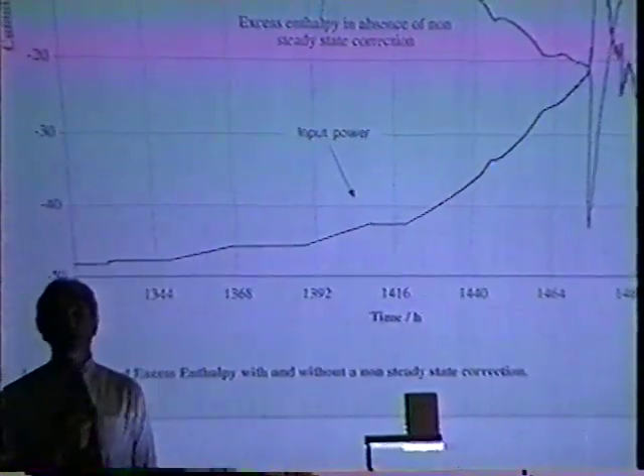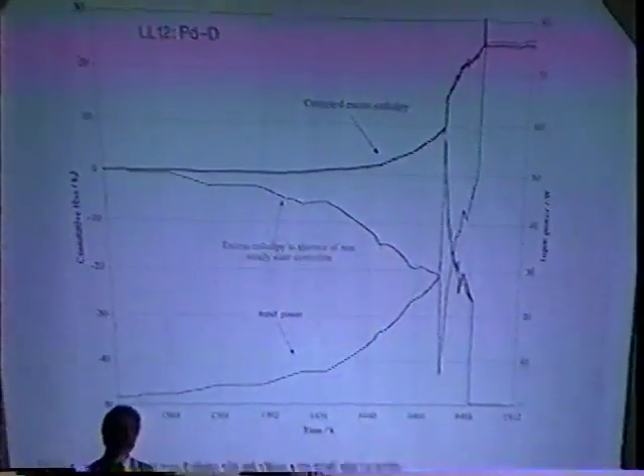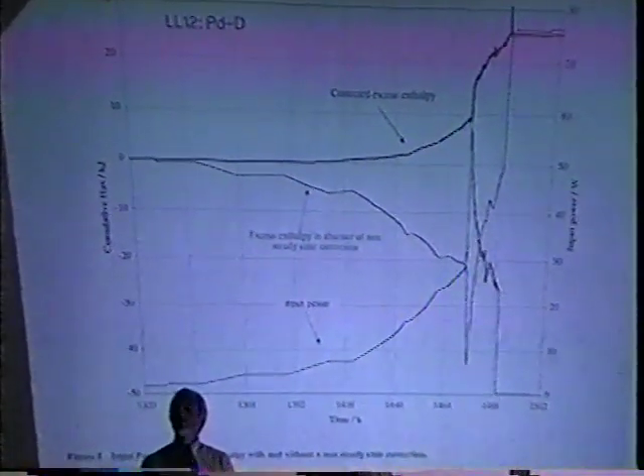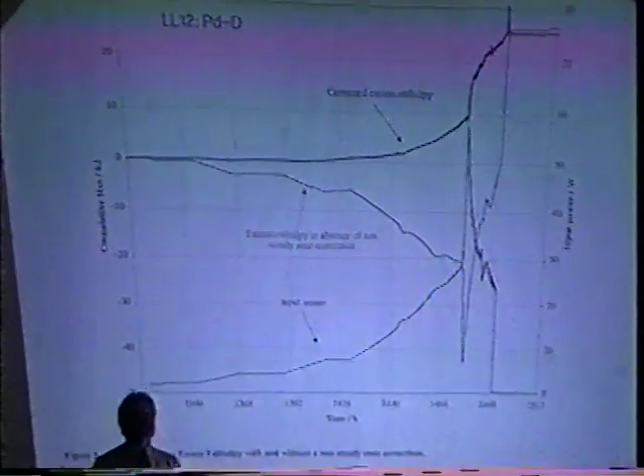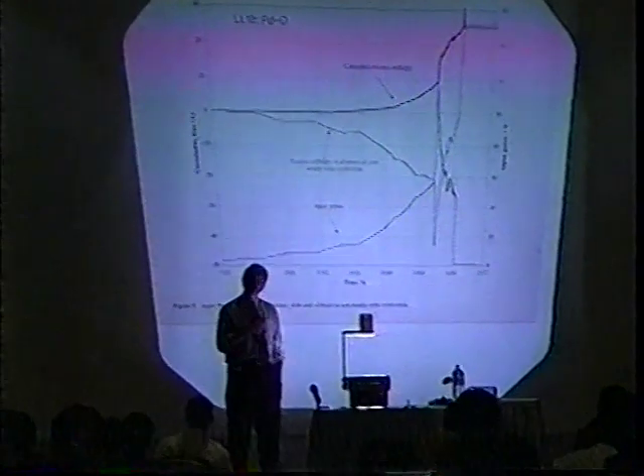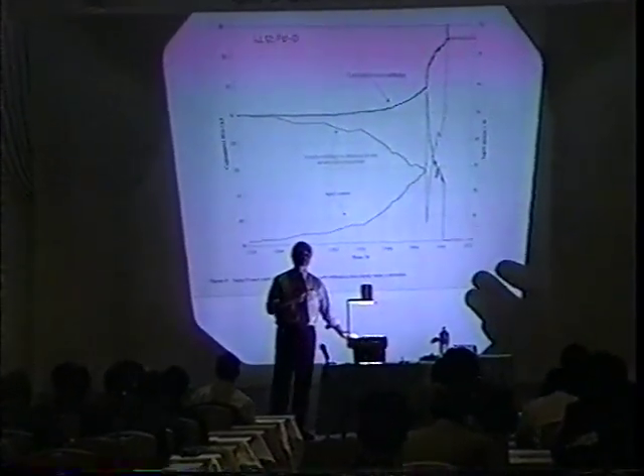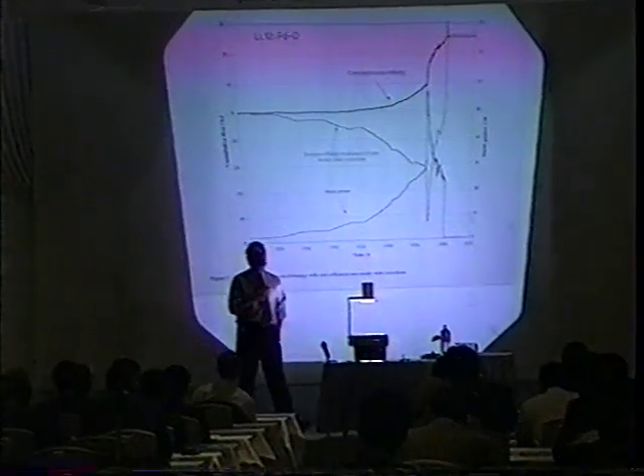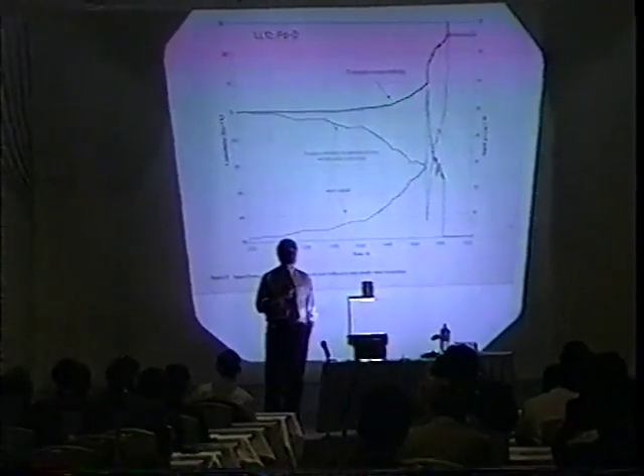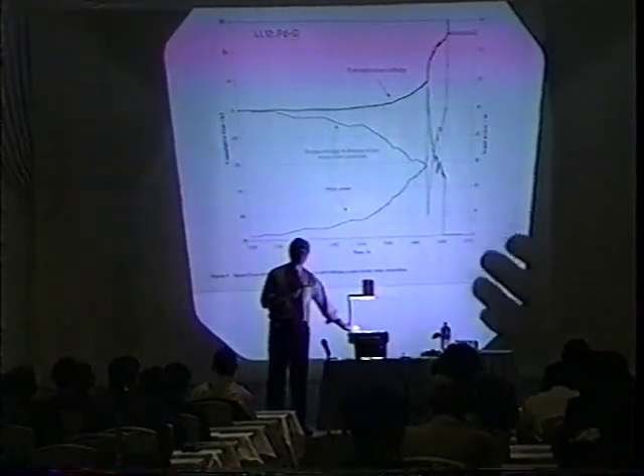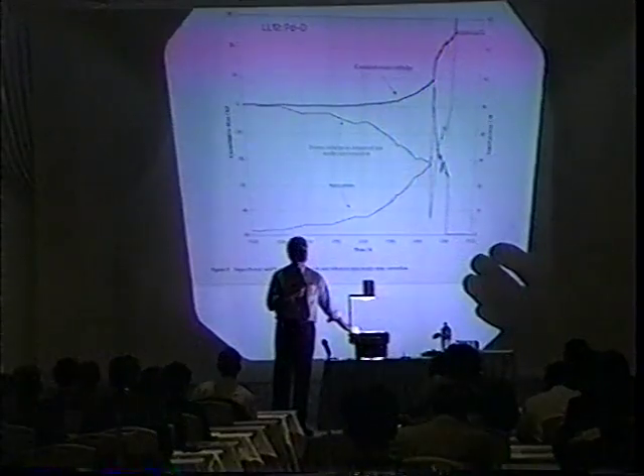We performed this experiment several times with other palladium cathodes. We observed no departures from the calorimetric balance when the non-steady state correction is done in exactly the same way. We've calibrated this method of data analysis by using a platinum cathode in the same calorimeter with the same non-steady state corrections, and we observed an exact thermal balance. So we're quite confident that, using our calorimeters, we are able to observe excess heat effects during the boil-off condition, rather similar to those reported by Fleischmann and Pons in Nagoya. Thank you very much.